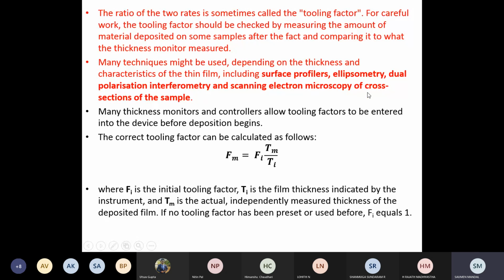Scanning electron microscopy with cross-sectional samples is a very effective technique, and it can give you the accurate value with the picture. If you make a cross-sectional cut and then go for scanning electron microscopy, you will get the thickness. Now, how is the tooling factor calculated? The correct tooling factor is Fm, which equals Fi, the initial tooling factor, multiplied by Tm divided by Ti. Tm is the measured thickness, and Ti is the thickness indicated by the instrument, like the FTM.